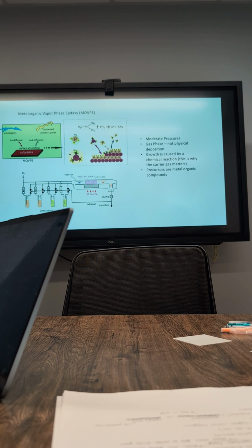Can you have like oxygen then, or does it always have to be nitrogen? I think in things like ALD, they'll spray like water and stuff in there. Oh, okay. So you can have oxygen, but this is where it can get contaminated and cause defects, which aren't great. But sometimes if your process is good enough and clean enough and your reactions are what you want them to be and everything's going in the right direction, you can get good crystal quality. And it's cheap. So it's more used than MBE for sure, even if you don't have this great of crystal quality.